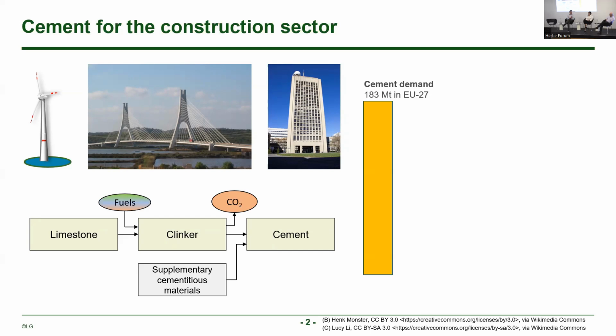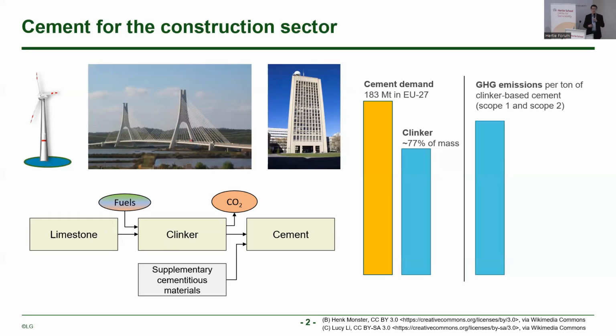If we look at cement demand in Europe today, we are at around 183 million tons demanded and used every year, of which about 77% are provided with clinker. If you look at the greenhouse gas emissions from clinker production, we have the process-related carbon dioxide emissions from the chemical reactions, up to 480 kilograms per ton of clinker. And then we have, on top of that, roughly the same amount, about up to 400 kilograms of carbon dioxide per ton of clinker of the fuel-related carbon dioxide emissions.